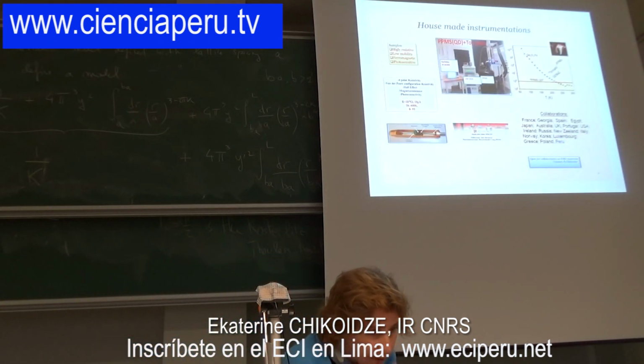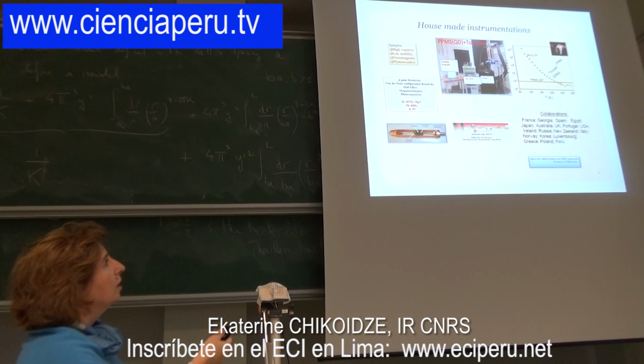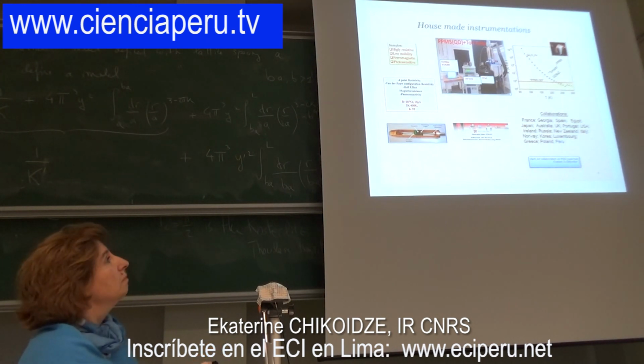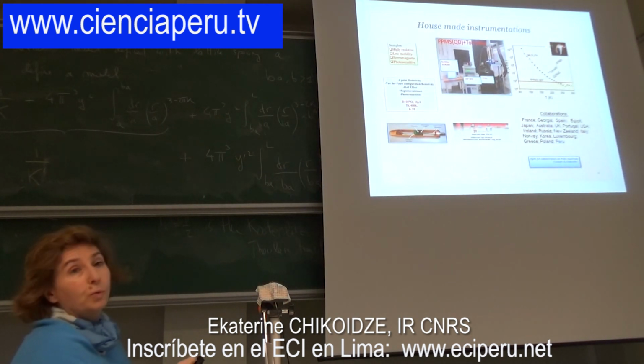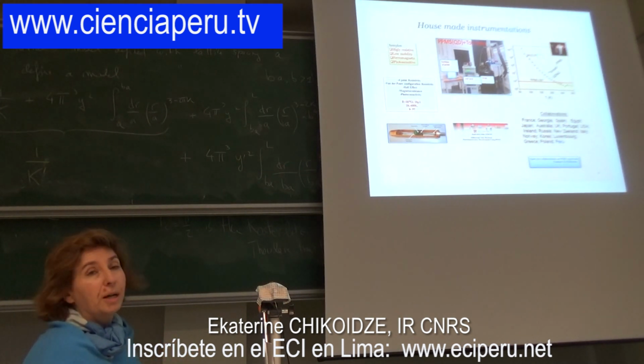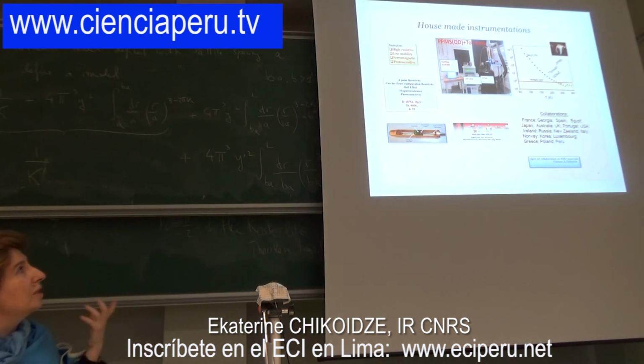And the third one is the conventional PPMS, physical property measurement system from Quantum Design, but which was updated specially for wide bandgap materials, it means for very resistive materials. When we bought it, we could measure up to megaohm resistance. After the option which I call Tornado, we can measure up to 10 gigaohm. The difference between Tornado and the previous one is that here we can apply a 9 Tesla magnetic field, and the current we can apply is picoampere, while in the previous one it is nanoampere.